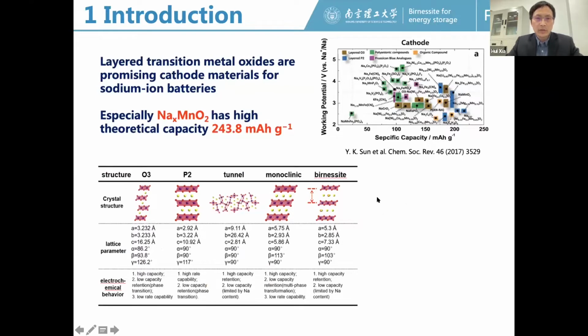For the electrode materials, the layered transition metal oxides are promising cathode materials for sodium-ion batteries. Especially, we are interested in sodium manganese oxide, which has a high theoretical capacity of about 243 milliampere hour per gram. And there are several different layered structures for this sodium manganese oxide, like the O3 type, P2 type, and monoclinic. For all these layered structures, they have a limited interlayer spacing of about 5 angstrom to 6 angstrom, which actually limits the sodium diffusion in the interlayer.